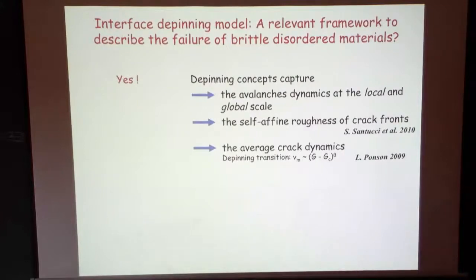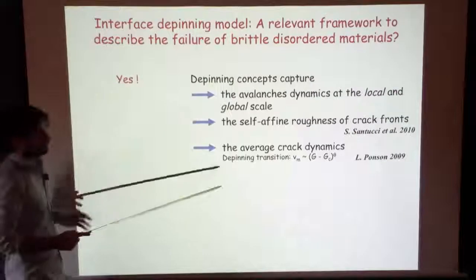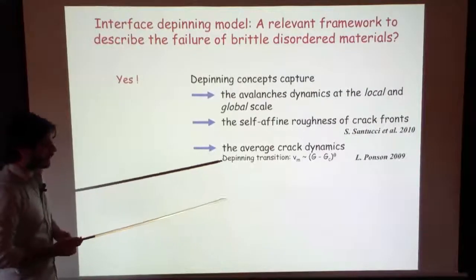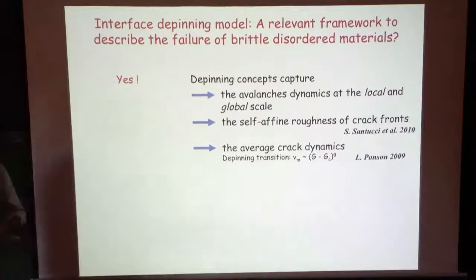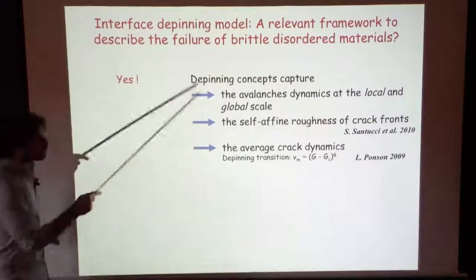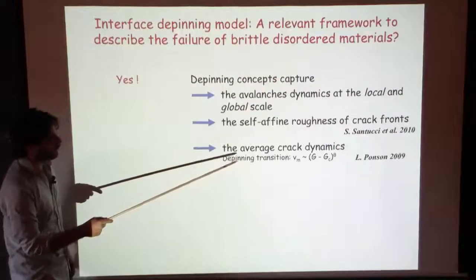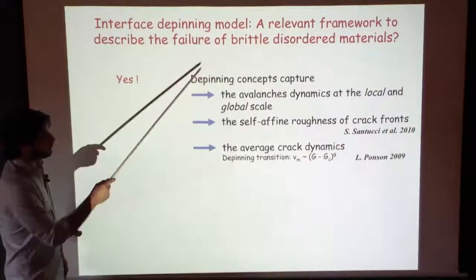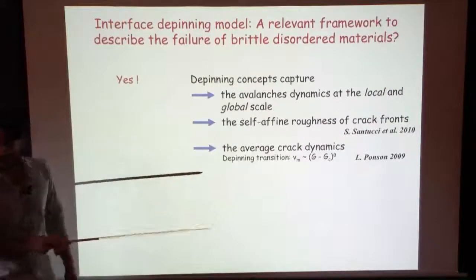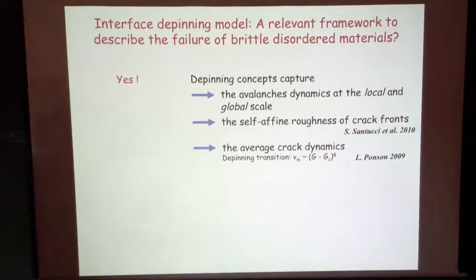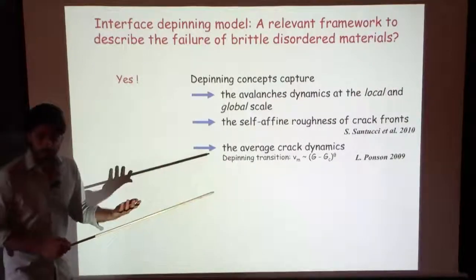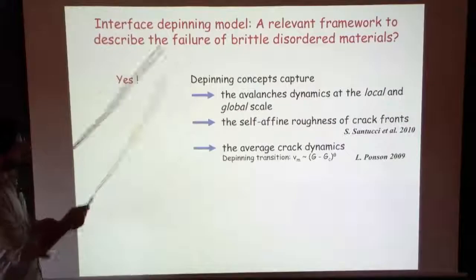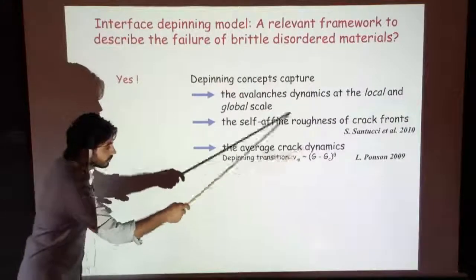We discussed the avalanche dynamics. It makes a rather good job of rationalizing all this experimental observation, up to the value of the exponent to some limit, but I would say it's a reasonable agreement. There are also other interesting predictions of the depinning model that work well on the crack front problem. Recently, people measured the roughness exponent, and they measured the 0.4 prediction that can be made from the model. You also have the average crack dynamics.